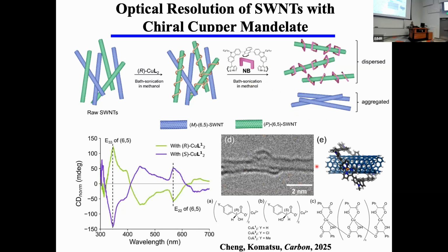So this is again the TEM structure of the interlocking carbon nanotube. And finally, we independently did this kind of extraction by use of the R copper mandelate and S copper mandelate, and dispersed and measured the CD once again, so that we can obtain this symmetrical CD. That clearly shows that this copper mandelate, in combination with another bracket, successfully recognizes the left-handed and the right-handed structure of the carbon nanotube.